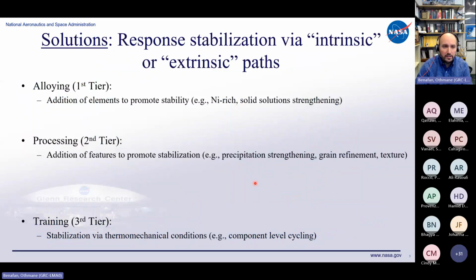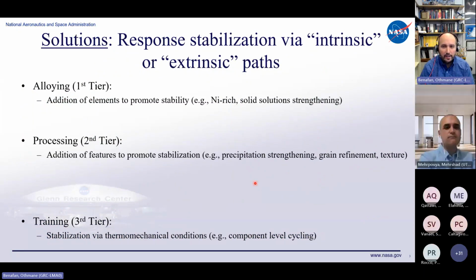So let's take a look at some solutions here. I just bin them into intrinsic and extrinsic. For example, the first solution is through the alloy itself. When we alloy, the first thing you start with is the alloy composition, the chemistry. So you add elements to, let's say, nickel titanium. You make an alloy nickel rich, for instance, so you can do solid solution strengthening, or you add other stabilizers like cobalt or what have you, depending on what region you're looking at. So that's the first line of defense against those challenges: your chemistry.